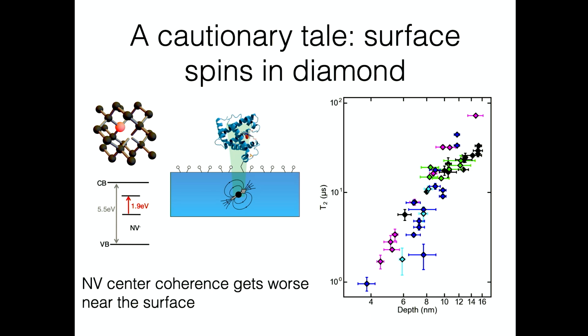And the reason that nobody can do it is because these really long coherence times that you have are really only true in the deep bulk of high purity diamond. And in order to do something like this nano MRI experiment, I have to bring this NV center really close to the surface of diamond. And what we see is that the coherence times get much worse as I come close to the surface. Okay, so everyone sees this problem. You have this horrible power law scaling. So instead of my milliseconds of coherence, when I get within a few nanometers, I have more like hundreds of nanoseconds of coherence, which is really bad.